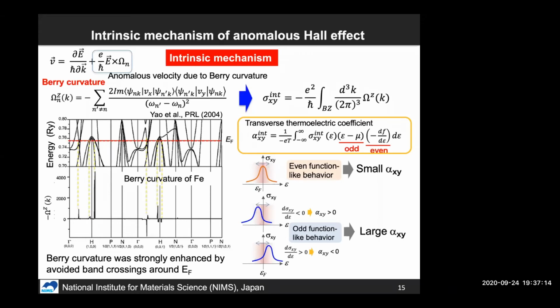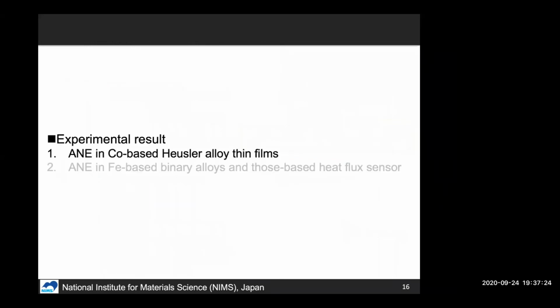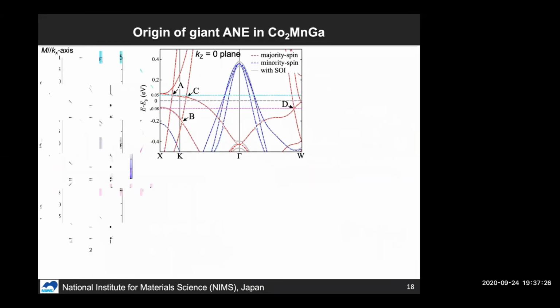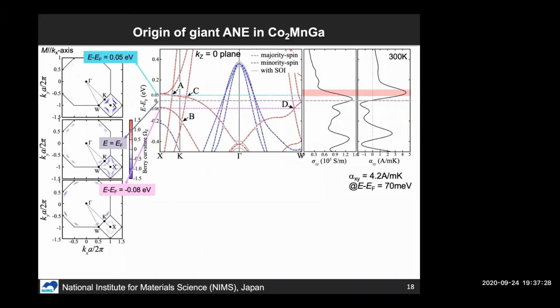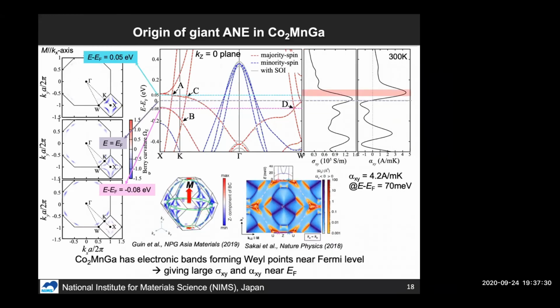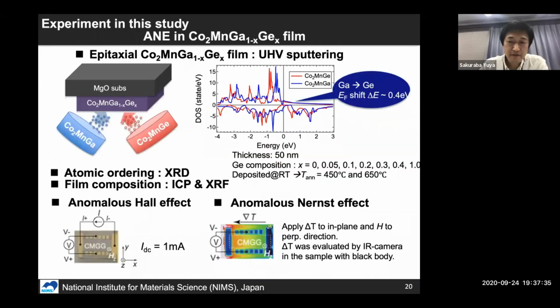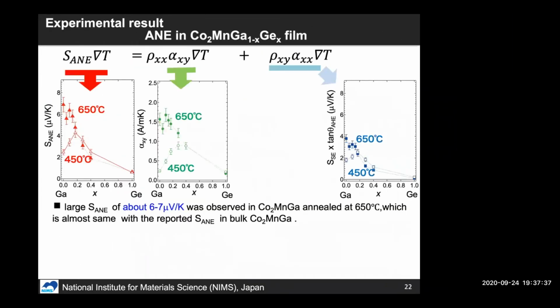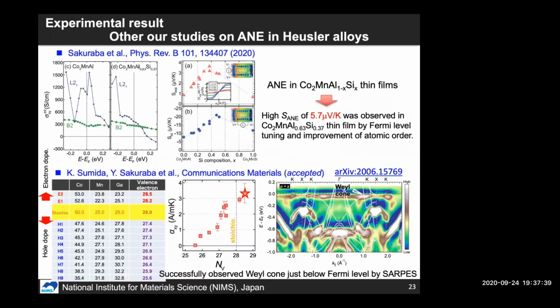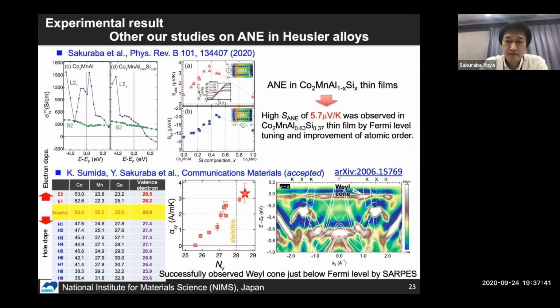First, quickly, you showed that ARPES data on your cobalt manganese gallium, I guess, where you said that there is evidence for Weyl points. I was wondering, did you see any Fermi arc states in these materials? If you have Weyl points, you should see Fermi arcs on the surface. It was also not very clear where exactly the Weyl point is. Maybe the data is not very obvious.